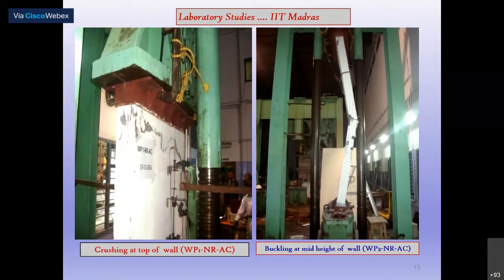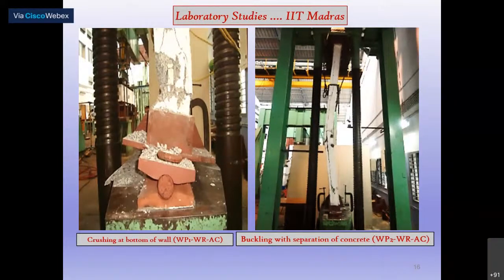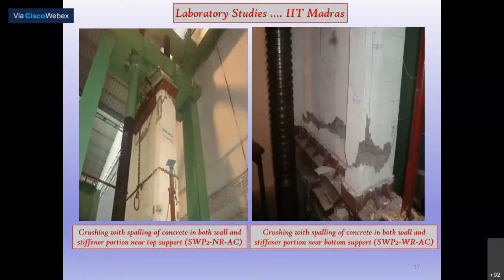This is a mega project we have done. Different walls were proposed and designed with different parameters involved. Then we tested short walls and long walls, and we understood their behavior. Then we proposed to go for ground plus 1, plus 2, plus 3, and up to 5. And we also needed to understand their behavior under cyclic loading. So these large size walls, almost 5 meters, 6 meters, were tested at IIT Madras.